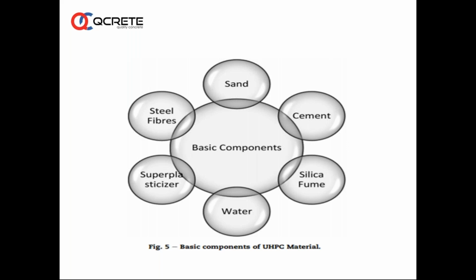And here we can say silica fume plays a major role in bringing higher and higher strength and higher performance into the concrete matrix. We have seldom seen much literature on ultra high performance concrete without silica fume. Most of the work across the globe is done mostly on silica fume, and very rarely we see products like metakaolin, or in combination with silica fume, some metals replacing it to some extent. So basically, these are the components of ultra high performance concrete.